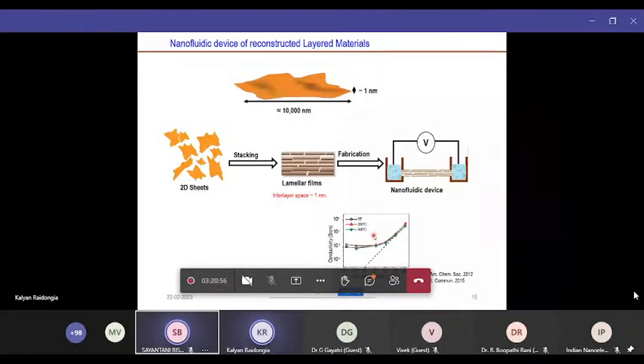So we'll just move on slightly now. Lots of people are adopting different methods to make channels with overlapping electrical double layers and using them for different applications. We have also developed different techniques, which are based on 2D layers like graphene oxide and boron nitride, BCN, vermiculite, MoS2, WS2, so many 2D materials that you know now, since everyone knows about 2D materials from all the talks. These 2D materials are very large sheets with a large length-to-thickness ratio. The thickness is just 1, 2, or at most 10 nanometers, and the width is tens of micrometers.